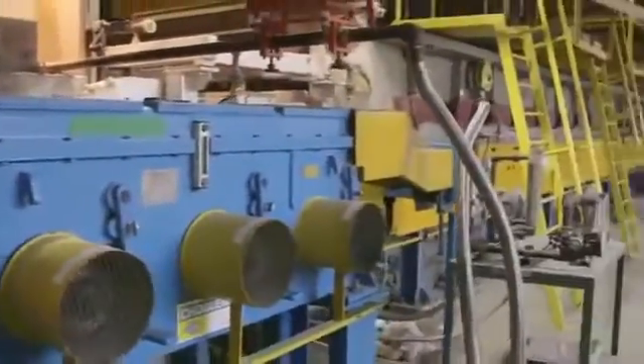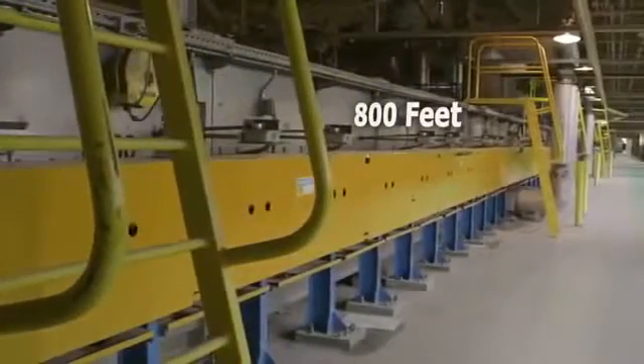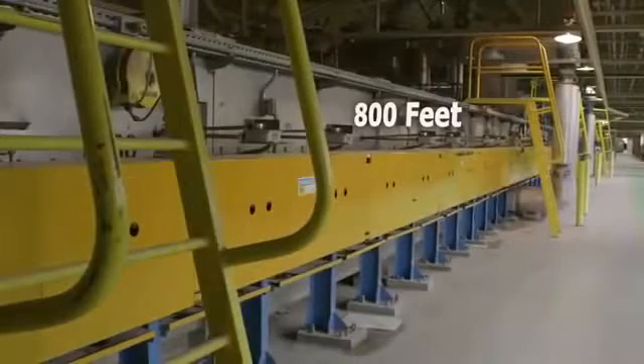The glass now enters the annealing lehr, where any stresses are removed by a controlled cooling process. In a length of over 800 feet, equivalent to 3 football fields, the glass is taken from 1,100 degrees Fahrenheit down to room temperature. At this stage, the glass is perfect.